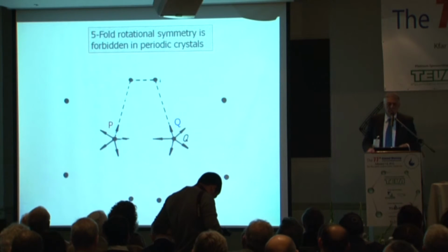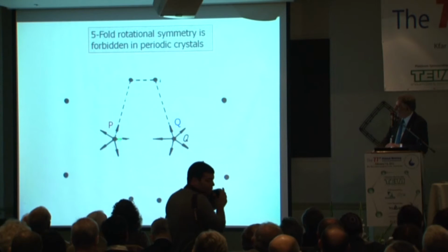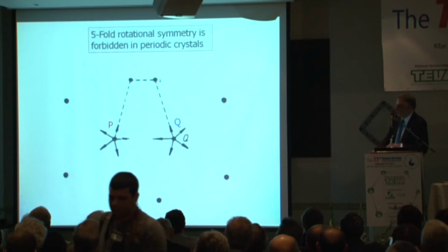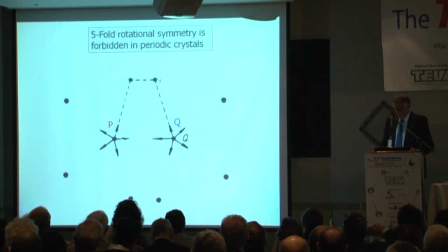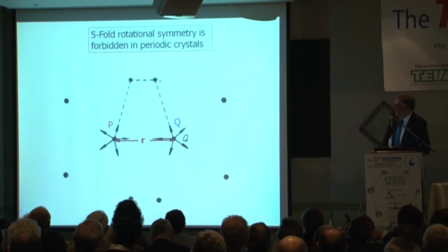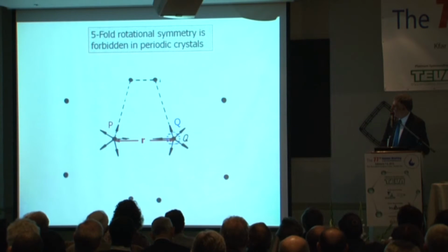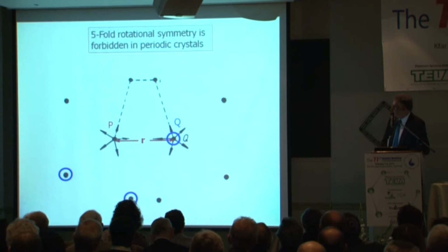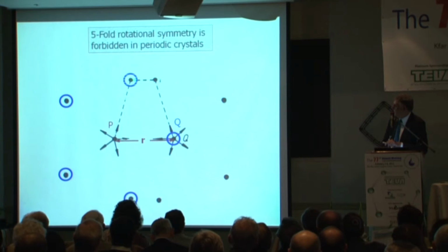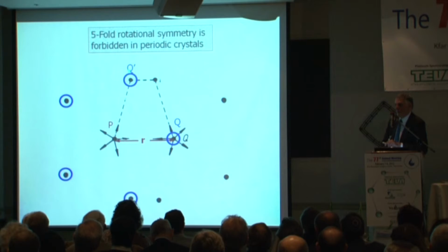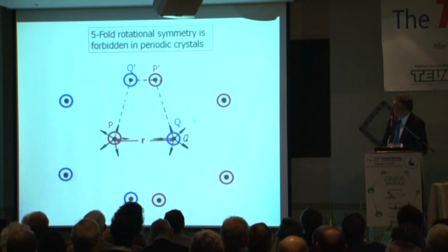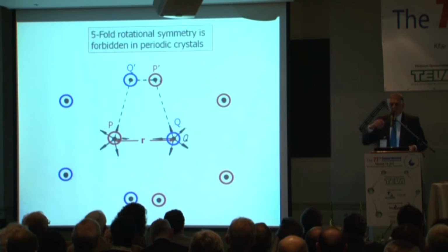You see, in order to prove it, there are other ways you can do that. I choose 2 atoms, P and Q, in the lattice, and I choose the 2 atoms that are closest together, the minimum distance between them. And that distance is this distance R. And now, if 5-fold rotational symmetry is allowed, then I should be able to rotate Q around P 5 times, and P around Q 5 times, and let's see what happens. So let's take Q and rotate it 1, 2, 3, here we go, 4 and 5, and we have Q prime. There should be an atom here, if 5-fold rotational symmetry is allowed. Also P around Q, 2, 3, 4, and 5, and there is P prime, and because of geometrical reasons, P prime, Q prime is closer together than PQ, which cannot be because I chose the closest atoms in the structure.